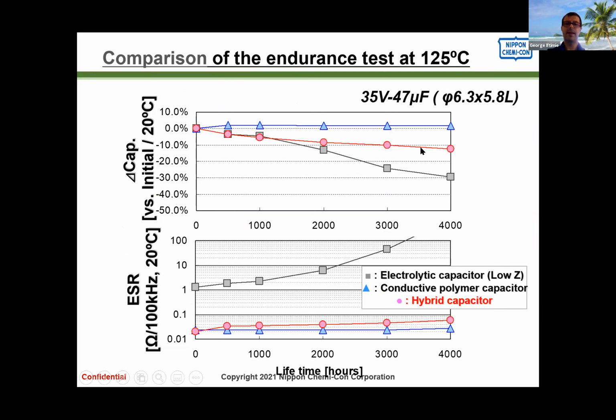This is an endurance test. And again, what you see, and I mentioned earlier a little bit, a polymer capacitor is basically flat. If you look at the blue line, capacitance, ESR, essentially whatever you started with, you're going to end with. On a liquid part, essentially you're looking at 30% change or so after 4,000 hours. And then you have a hybrid part, which is a little bit in the middle. Capacitance, of course, is going to be almost in the middle. The ESR actually does not change as much, especially compared to an electrolytic. One thing to keep in mind here is that the electrolytic couldn't even survive 4,000 hours before it went out of spec.